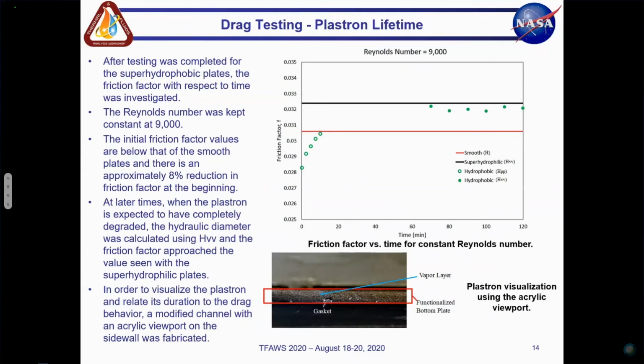So we kept the Reynolds number constant at 9,000. Originally, we saw an 8% drag reduction in the friction factor at the beginning. And then at later times, as the plastron starts to degrade, or roughly around 10 minutes, you see this shift towards fully wetted, where we use HVV to calculate the friction factor. And you see that fall just below the superhydrophilic at times 60 minutes or greater.